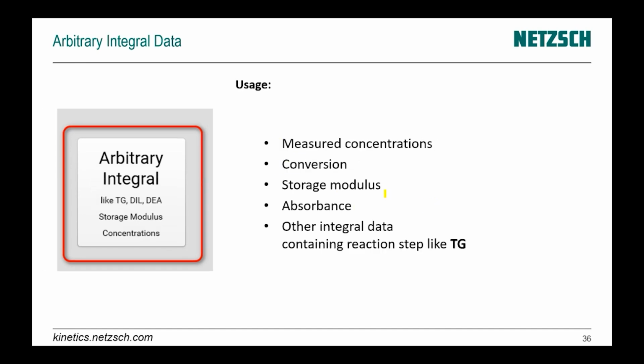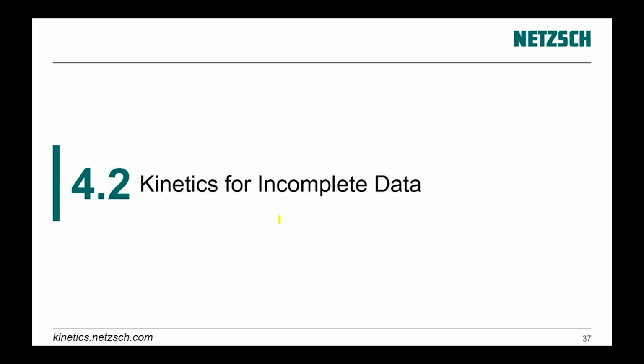Arbitrary integral data could be used for the data where a reaction curve has a step, like TG. For example, it could be measured concentrations. You can measure concentration outside of DSC or TG, for example, by optical methods. And after that, you can put these curves into our Kinetics Neo software and then make kinetic analysis. You can measure conversion, degree of conversion. You can measure, for example, storage modulus, absorbance during FTIR, or other integral data.